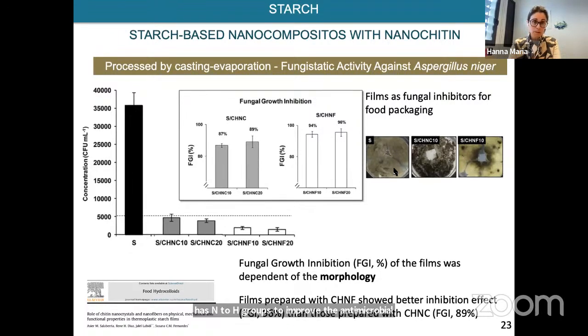And we can see here on the right side, in this case, we didn't use bacteria. We used fungi to see if the fungi grew at the surface. And you can see here in the starch film, with time it was almost covered by the fungi, and with 10% of chitin nanocrystals or chitin nanofibers, we can see that the film is protected. The fungi can't really cover the whole film.